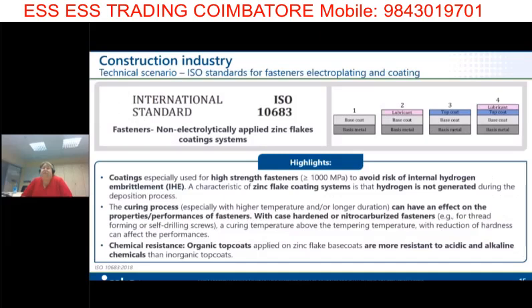The next is the ISO 10683, which is somehow familiar and similar to the ISO 4042, but here it's dealing with zinc flake coated fasteners. Means when you have on top of your base material a base coat or a top coat. They are giving the hints that you can use the coating here also for high strength fasteners, because one really positive effect of applying zinc flake coatings on your fasteners is that there is no hydrogen generated, and so the risk of internal hydrogen embrittlement is avoided.